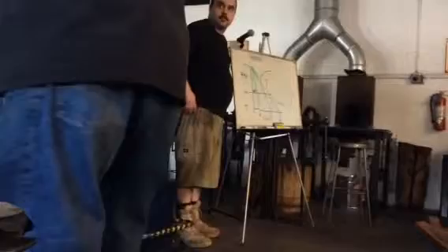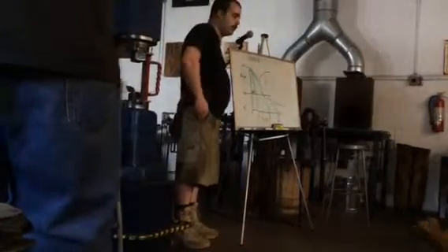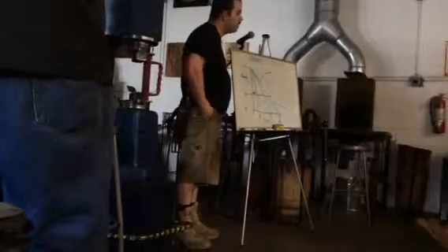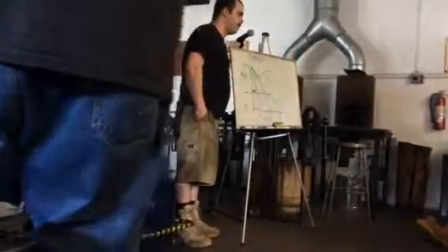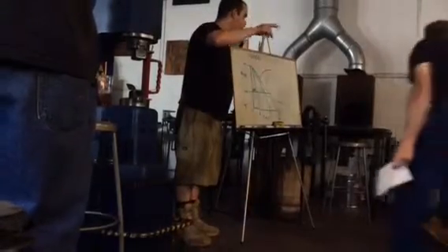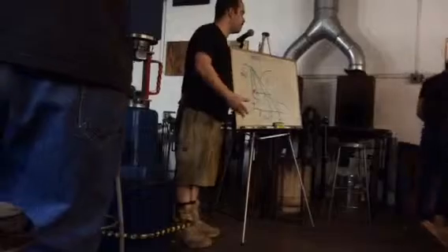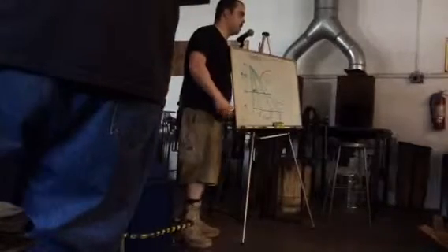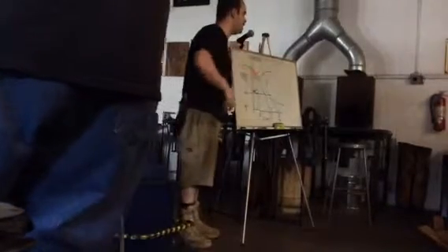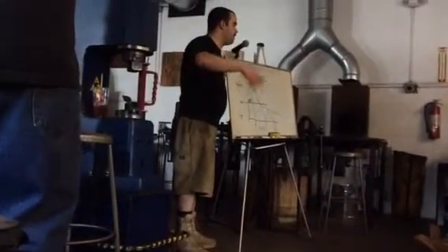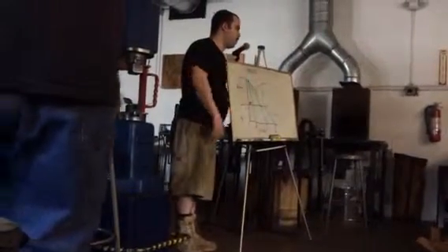I think maybe what we'll do is try to find a piece of steel and show them through the grain line. Normalization is always like a three-step. Usually a good rule of thumb is that folks are just doing normalizations, one higher and then lower and so forth. If you have really good control in a kiln, ideally it's good to reset the grain heavily at 1600 or 1650, right? Walk it down to 1550, 1500, and maybe 1450.